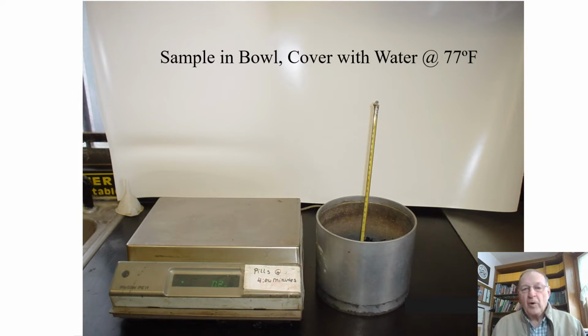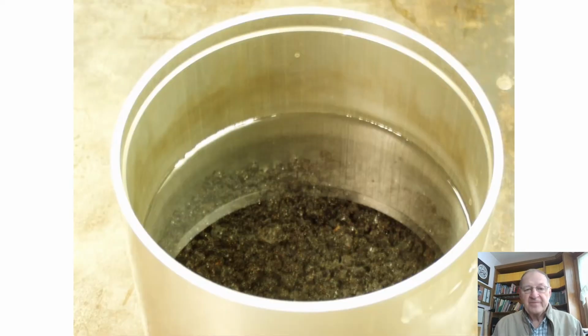We put it in a bowl and cover it with water, and this is done at 77 degrees. Here you can see the sample sitting underwater. And then we're going to vacuum that sample for 15 minutes with agitation. The device with the blue handle there is the vacuum pump, and there's an air drying system that you see up on the shelf, and a pressure gauge on top of the lid that is held down. The bowl and the lid and everything sits on top of an agitator, and it shakes the sample as it's being vacuumed.